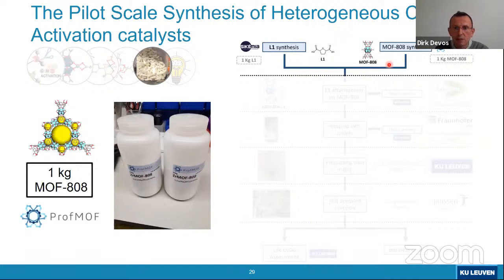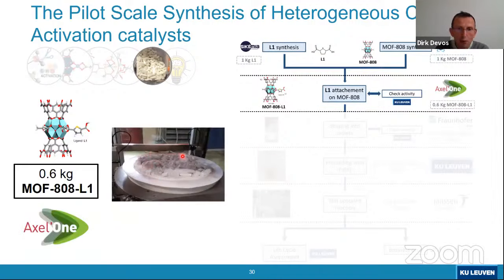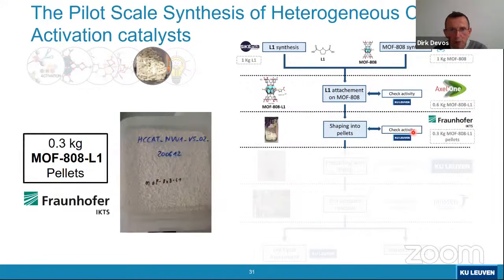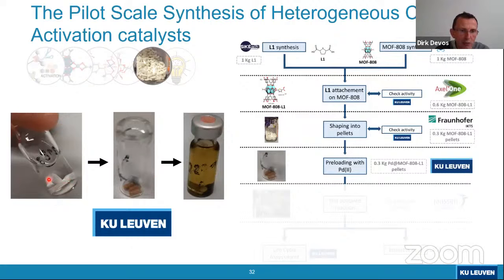Same story a bit for the MOF. The MOF, you could think this is exotic, but actually no. The zirconium MOF with benzene tricarboxylic acid was made by our colleagues, by Karl Petter Lillerud in Norway, with a company called MOF Technologies, a small company specializing in these MOF syntheses. They made it at a sufficient scale, which meant that we had a lot of this MOF powder that we could functionalize with the ligand, which was then actually shaped into pellets eventually. And so together with partners like Axel'One in France, but also the Fraunhofer Institute, they eventually made this into pellets of the MOF that we then loaded with palladium. And so here you see a couple of these pellets.